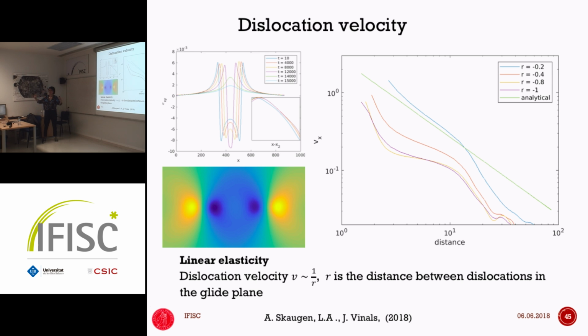So they go faster and faster and faster towards the annihilation point. It's like a runaway behavior. And it's very far away from it. The deeper the quench, the more significant deviations we have. The lower the quenching depth, we see that at some point it does look like the prediction. So we start here, initially they're far apart, and then as a function of time, they're going to move closer to each other until the annihilation point, right?